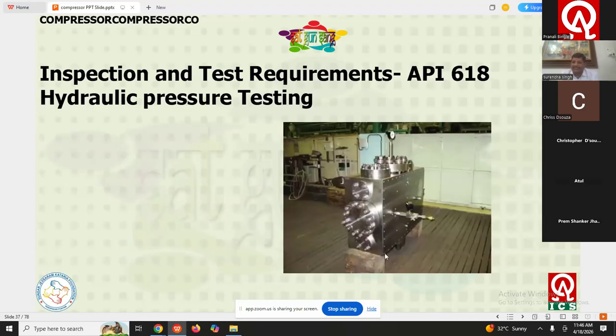In this picture, you can see a reciprocating type compressor under hydraulic testing. The gauge is mounted and then pressurization is done. This is a typical picture, and the holding time may be from 1/2 to 4 hours depending upon the customer as well as the API requirement. API 618 states that the pressure holding time shall be 30 minutes, but the customer can give their own requirement, which may be more stringent. So first check the QP to see what time is written for holding the pressure.